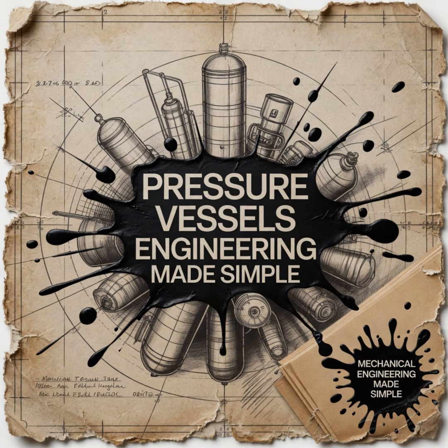But then the formula adds the percentage of molybdenum and multiplies it by a factor of 3.3. Why does molybdenum get such a massive multiplier in the fight against pitting? Because if chromium is the shield, molybdenum is basically the emergency patch kit. When a chloride ion manages to break through the chromium shield and starts drilling a pit, the environment inside that microscopic pit becomes highly acidic very, very quickly. And the chromium dissolves in that acid.